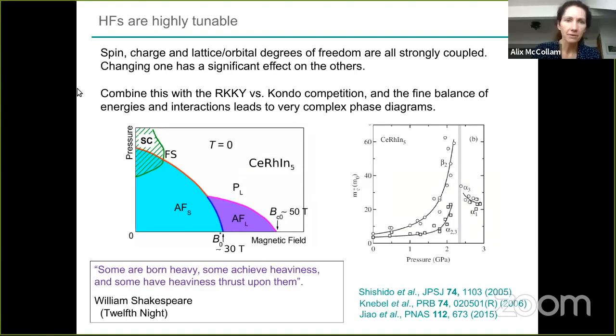This is a phase diagram for cerium rhodium indium 5. I put the references down here. It's a schematic phase diagram, but it shows high pressure versus magnetic field. At ambient pressure and zero field, it's an antiferromagnet, but as you increase the pressure, you suppress the antiferromagnetism, and superconductivity will appear here. If you increase the magnetic field, you also suppress the antiferromagnetism, and there's some change measured in the antiferromagnetic state before you suppress antiferromagnetism completely at very high magnetic field.